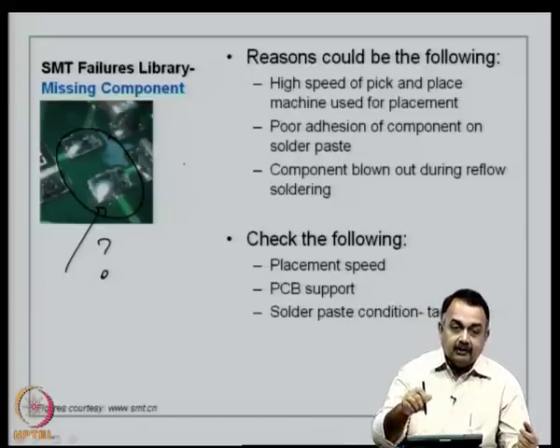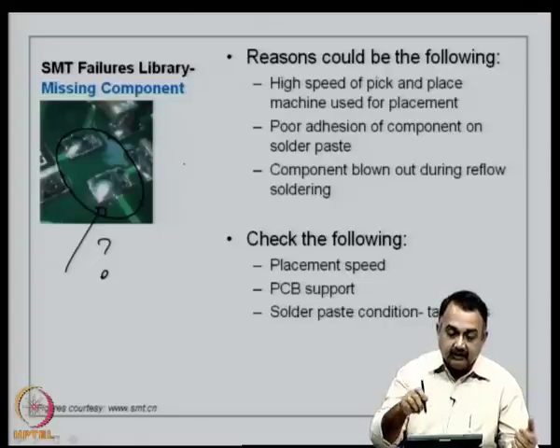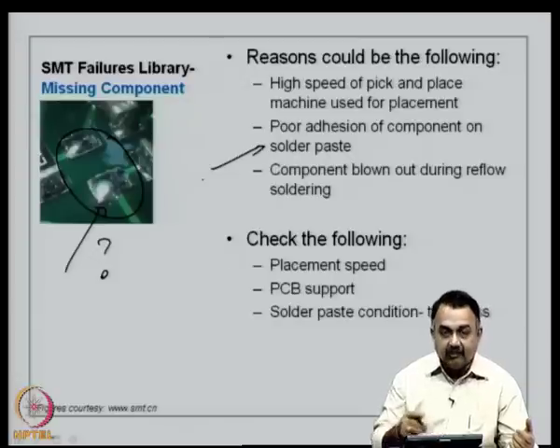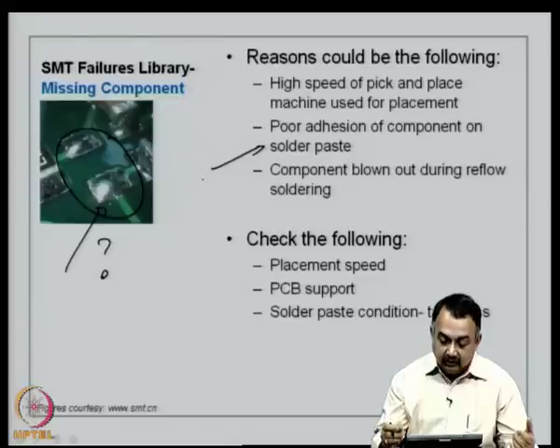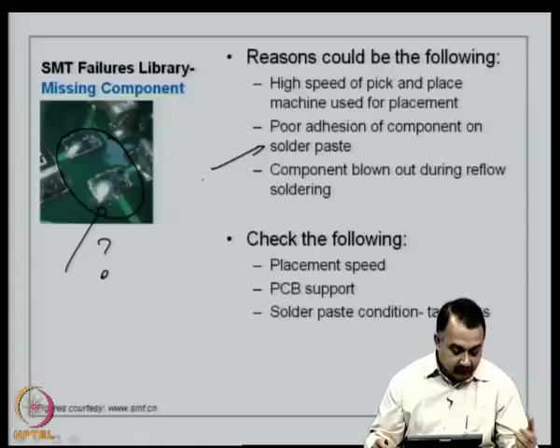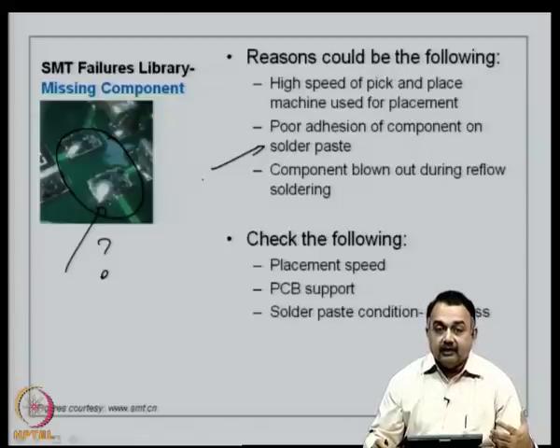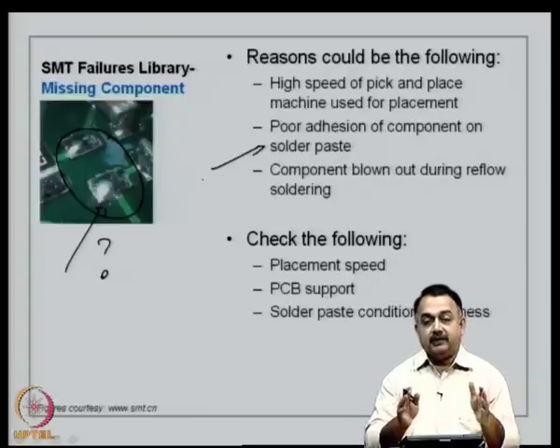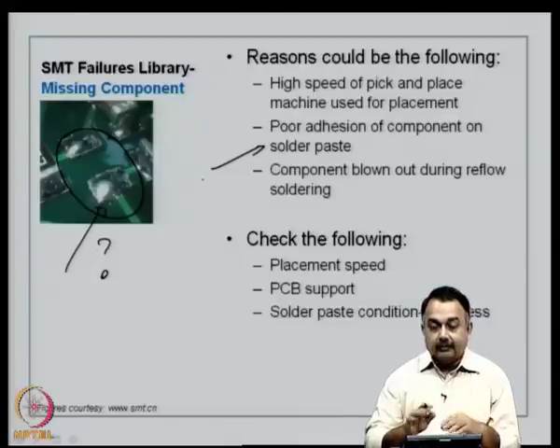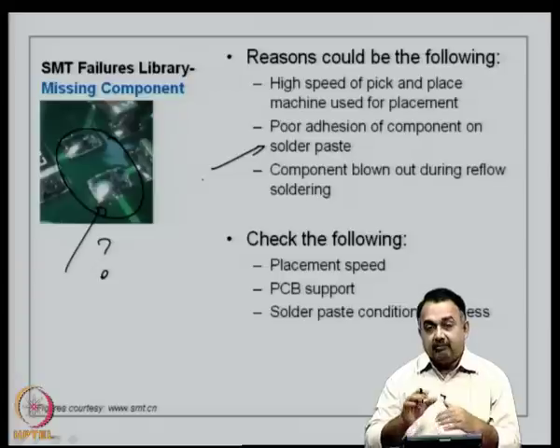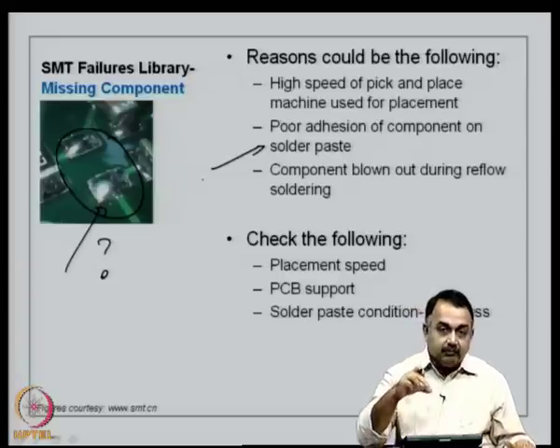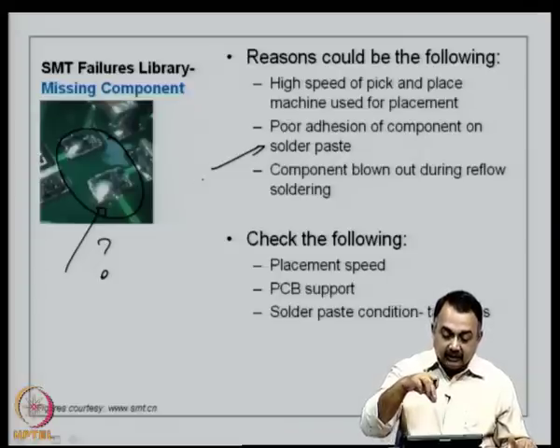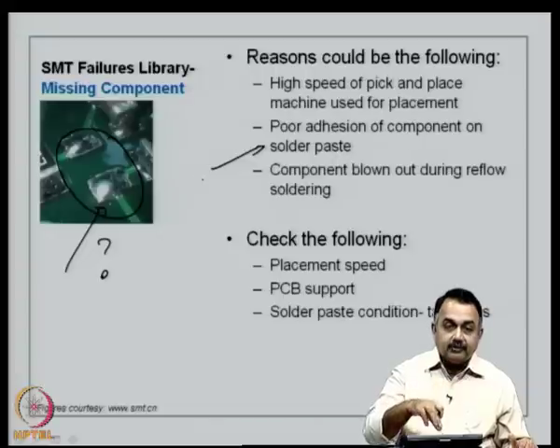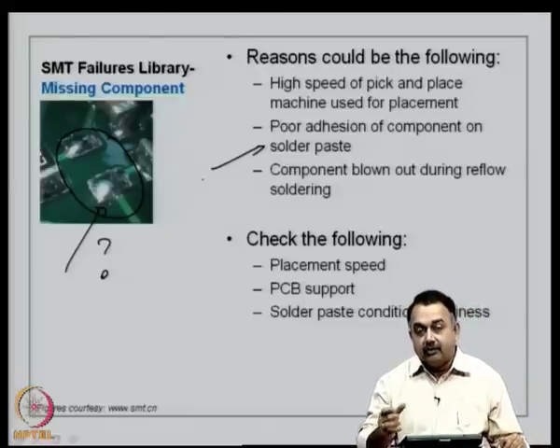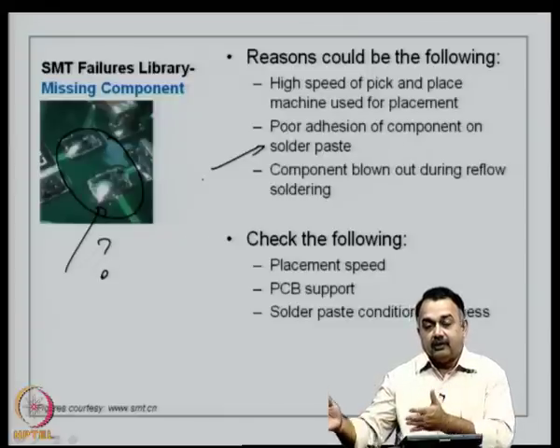Now, when you place a component either by the automated machine or manually, you are placing it on a solder paste. Now, the solder paste is supposed to have some kind of a tackiness to hold the component. So, in this case, typically if you troubleshoot, you could probably think that this solder paste does not contain enough adhesive to hold the component. Remember, in a pick and place machine, the speeds are very high. And normally the pick and place nozzle or the head does not position your component on the coordinates. It actually comes to the coordinate and then actually drops the component, and the component by its weight has to sit on the solder paste, and the solder paste with its adhesive component should hold the package until it goes for reflow soldering process.